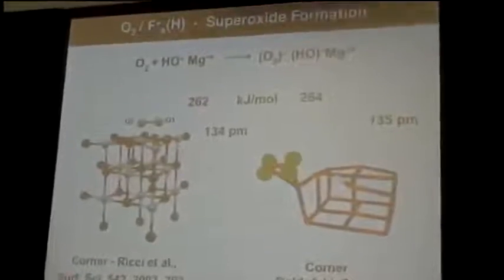And what happens then is that this electron moves to the oxygen and forms the superoxy species. And this is my message. The active species is probably this superoxy species. If you take the two reaction energies together, you find that this is a favorable process.